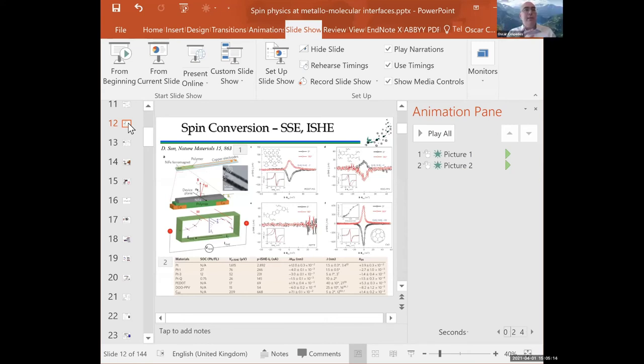Well, there are two different things there. One is the intrinsic spin orbit coupling of C60, and the other is how C60 enhances the spin orbit coupling of a metal. And that is also controversial because one could say there is some Rashba effect where you have an interfacial dipole and your molecules are changing the Rashba effect. And that is affecting the effective spin orbit coupling, not the actual atomic spin orbit coupling, but when you do measurements that depend on the spin orbit coupling, like spin scattering or spin Hall magnetoresistance or spin transfer torque, those measurements will depend on these interfacial effects.